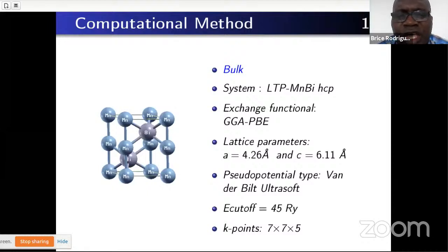The pseudopotential type is Vanderbilt ultrasoft. And the cutoff energy was 45 Rydberg. And the k-point sample was 7x7x5.